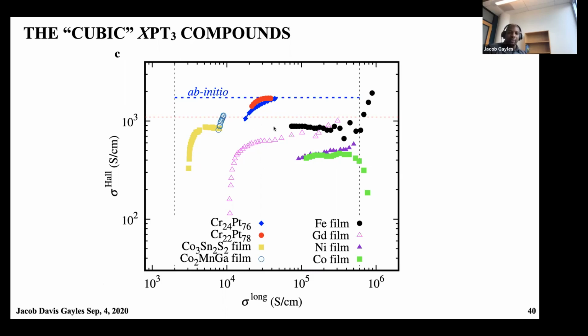And interestingly here, what you see for the chromium platinum is that it exists directly in the middle of these two bands. And if you remember from the band structure, you saw that we had these topological bands, but we also had other bands that interacted there at the Fermi level. So it's kind of a mixture between these two materials.